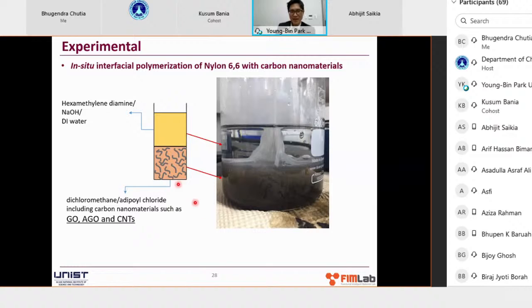So what happens is, as you pull some of the material up through the interface into the aqueous solution, the interface is where the actual polymerization takes place. So the whitish material produced here is the actual polyamide 6,6 material. In this case, because we have carbon nanomaterials dispersed in the organic solution, the final polyamide 6,6 will contain the carbon nanomaterials.